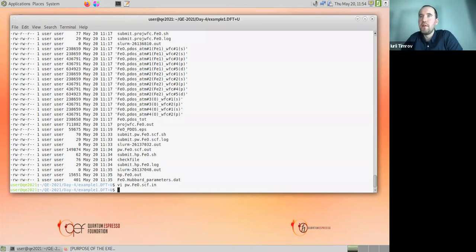Yeah, then the question, can the Hubbard U value be different according to the applied pseudopotential? Yes, the Hubbard U parameter depends on pseudopotentials, depends on the Hubbard manifold, if it's atomic or orthoatomic, depends on the oxidation state. So when you report the value of the Hubbard U in your paper, always remember to report which pseudopotentials you used, which functional, which Hubbard manifold, etc., so that people can reproduce your results. Otherwise, if you just report U equals 5 eV and that's it, that's not satisfactory.